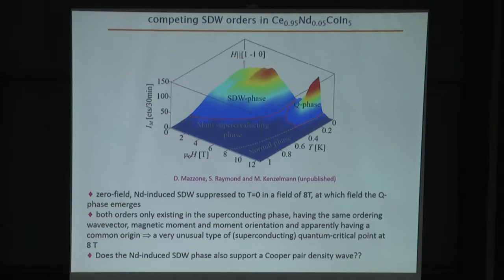Because the symmetry of this neodymium-induced spin density wave is identical to the symmetry of this field-induced spin density wave, this implied quantum critical point at 8 Tesla must be a rather unusual type of quantum critical point, because one cannot have a quantum phase transition between two ordered phases of exactly the same symmetry. And so this implies that this quantum critical point must somehow involve superconducting degrees of freedom.